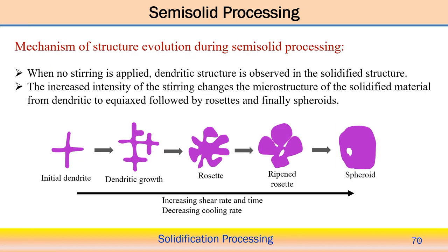Now, how does it work? The mechanism of the structure evolved during semi-solid processing. We can understand in which direction the structure forms in semi-solid processing. Suppose there is no strain applied. Sometimes during solidification the strain is also applied, that is, stirring is applied, in order to modify the solidified structure. When there is no stirring action applied, we can observe that a dendritic structure is observed in the solidified component.